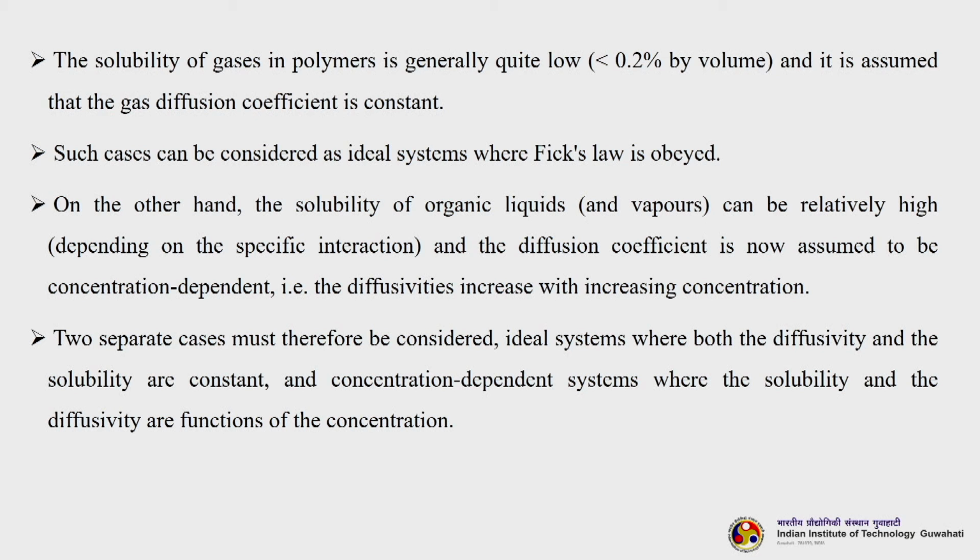The solubility of gases in polymers is very low, less than 0.2% by volume, and it is assumed that the gas diffusion coefficient is constant. Such cases can be considered as ideal systems where Fick's law is obeyed. On the other hand, the solubility of organic liquids and vapors can be relatively high depending upon the specific interaction, and the diffusion coefficient is now assumed to be concentration dependent, that is, diffusivity increases with increasing concentration. Two separate cases must therefore be considered: ideal systems where both the diffusivity and the solubility are constant, and concentration dependent systems where the solubility and diffusivity are functions of the concentration. So, we will discuss these two things.